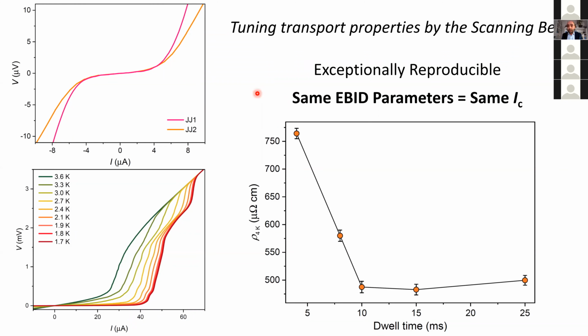But here it doesn't. Time and time again, we use the same parameters and we get the same thing, which, in a way, at first surprised me, because this is, as I said, a very disordered and dirty system. In fact, more than 50% is made of carbon and oxygen. And we're doing all the depositions at 10 to the power of minus 5 millibars, so it's not even in UHV.